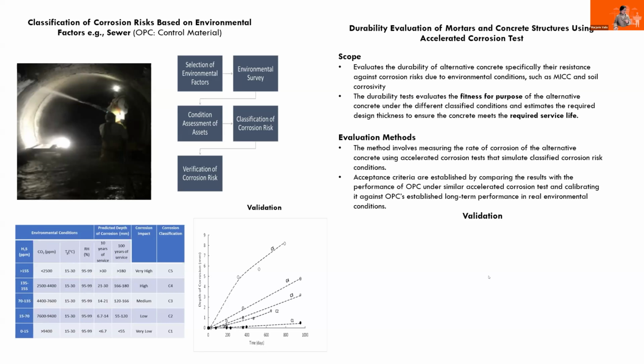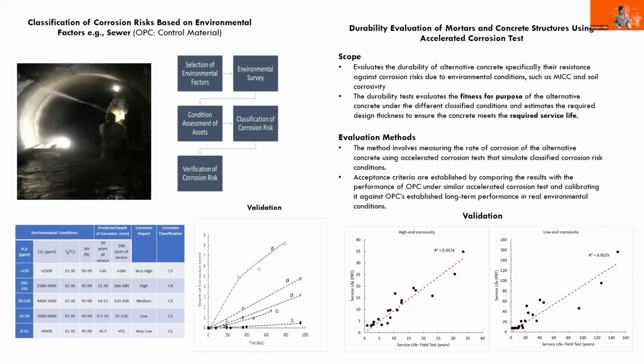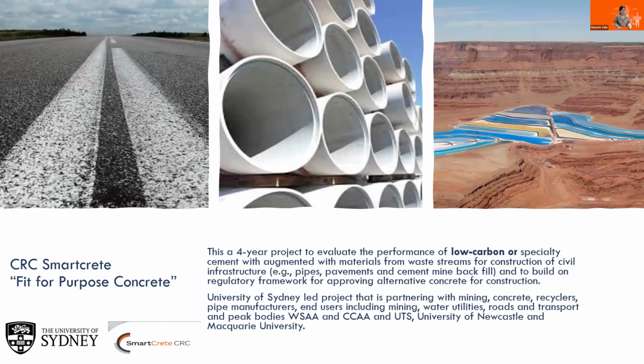So in terms of validation, it just shows you, for example, a high-end corrosivity test where we compare the service life of a particular asset or particular material and compare that to the service life we would predict using this accelerated corrosion test. At the high-end corrosivity, this represents, by the way, different types of cementitious materials, OPCs, and different alternative concrete, so I haven't tried to distinguish one from the other. And then this one is part of a low corrosivity comparison. So we could see that it's not a perfect fit, but we do have a reasonable fit that shows us that at least the trends are going in the right direction. Okay, so the question is, what's next?